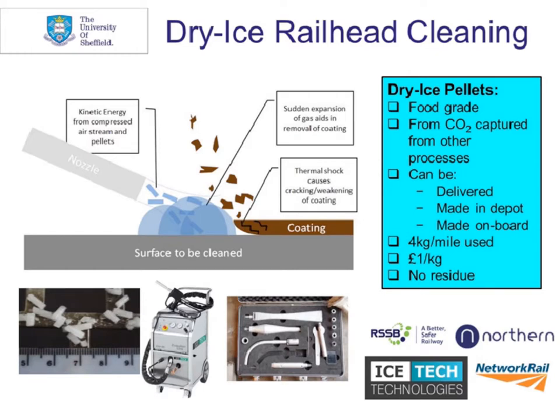And we've developed a technology based around cryogenic treatment, so firing dry ice pellets at the railhead to clean off leaf layers and oxide and water. So essentially we're firing very cold solid CO2 particles at the surface. Because they're cold, they embrittle the surface. They're coming out at supersonic speeds due to the nozzle design, so you've got a lot of kinetic energy there breaking up the brittle coating. And then the particles themselves, as they sublime and turn back into a gas, create these mini blasts. So you've got an increase of volume of about 800% during the sublimation process. So a number of mechanisms combine there to give really effective cleaning of the railhead.